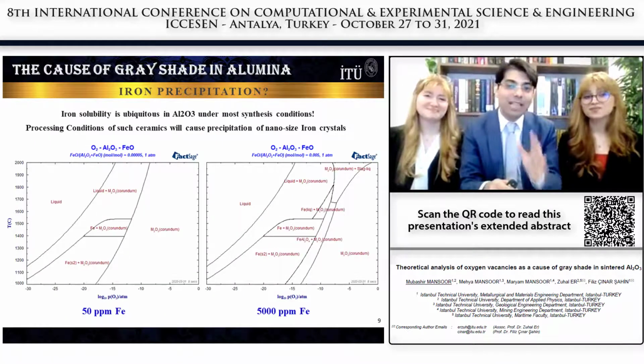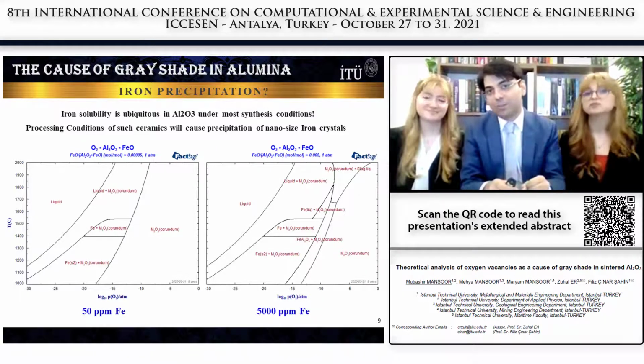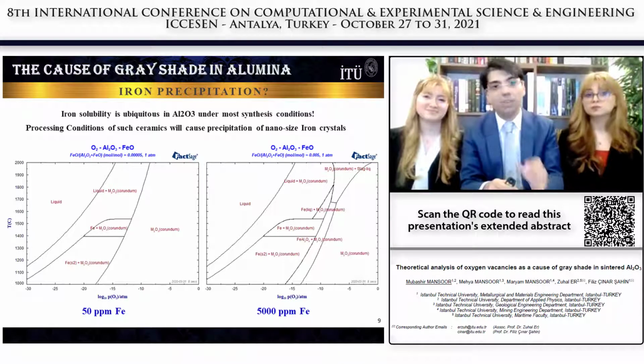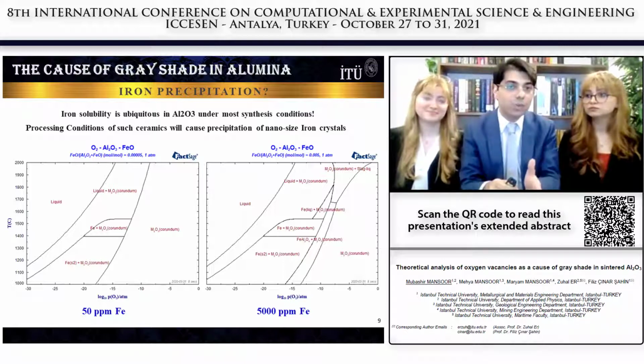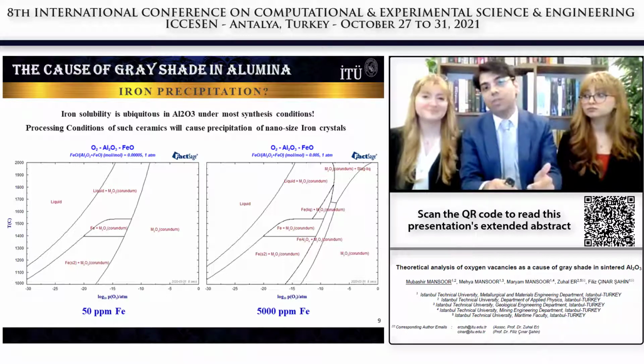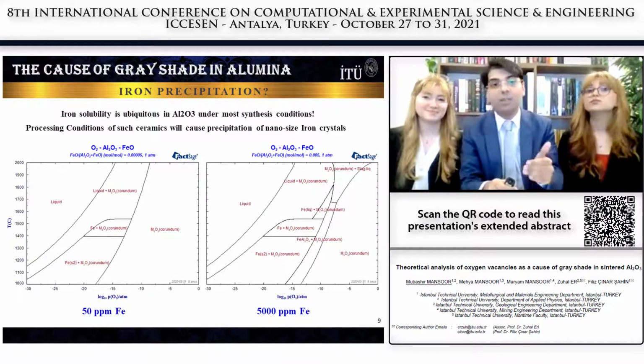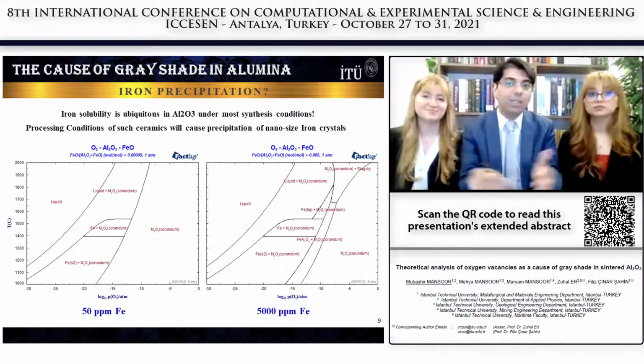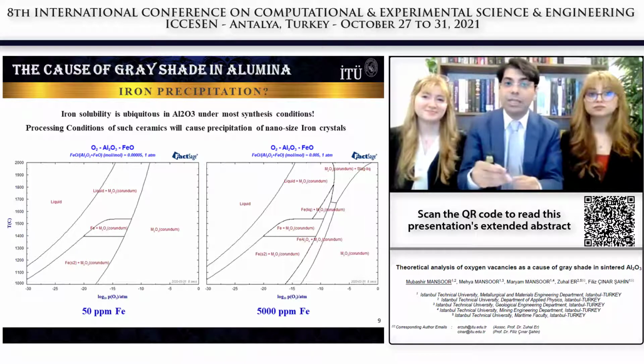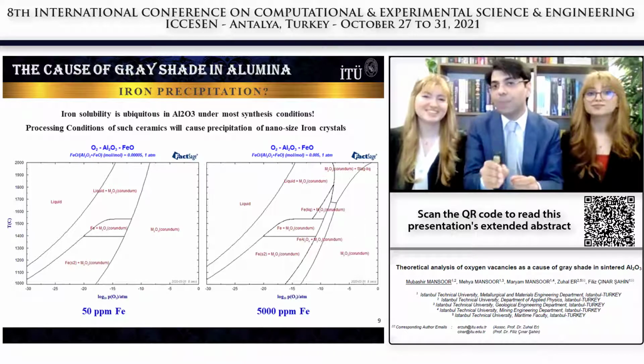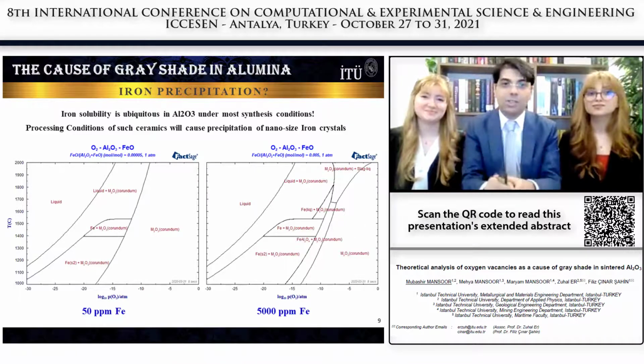Now, we would like to bring your attention to the alumina-hematite phase diagram. Iron oxide has a very high solubility in alumina under most conditions, and under the majority of powder synthesis routes, even up to 5,000 parts per million of iron can get dissolved into alumina if there is enough iron contamination available during the powder synthesis process. So this high solubility turns out to be very much oxygen dependent, as we see in our FactSage calculation.